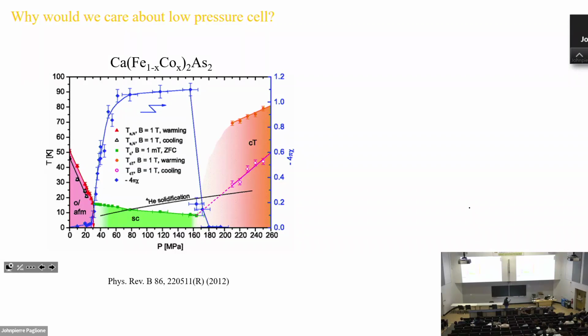So if you look at the scale, this is mega pascal. So in terms of GPa, this is 0.2 GPa. That's really small pressure. Using a diamond anvil cell for this, it's not a good idea.